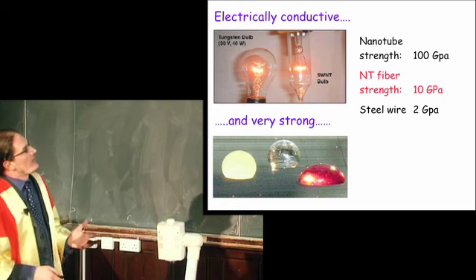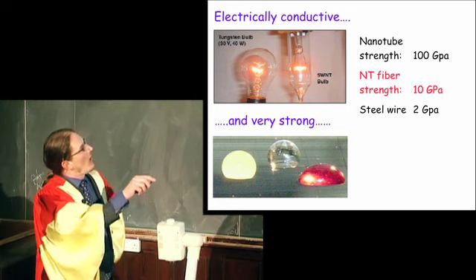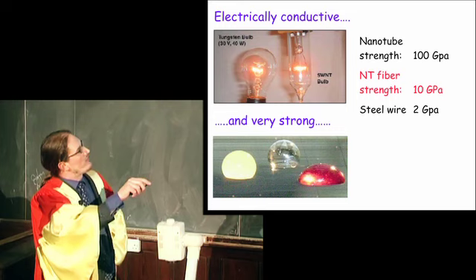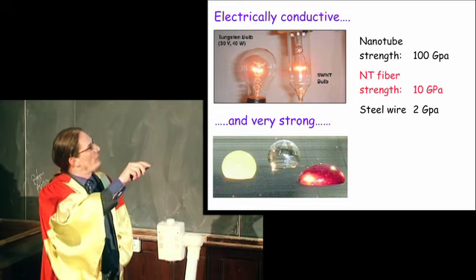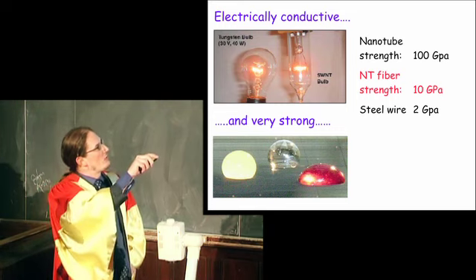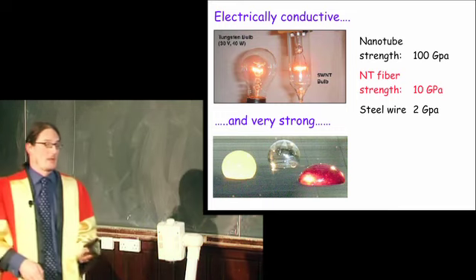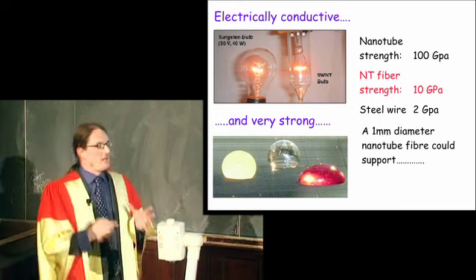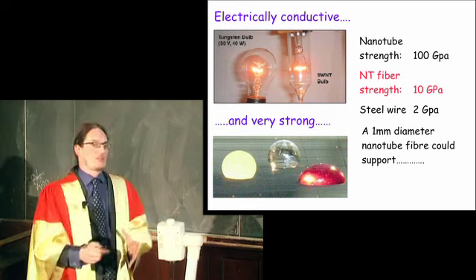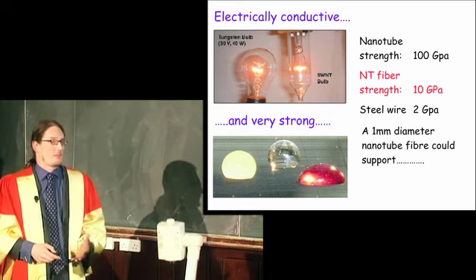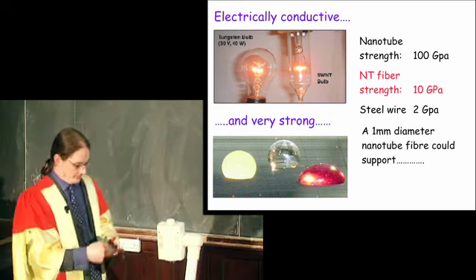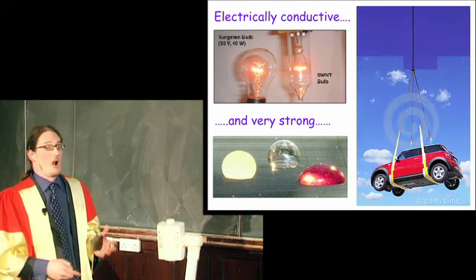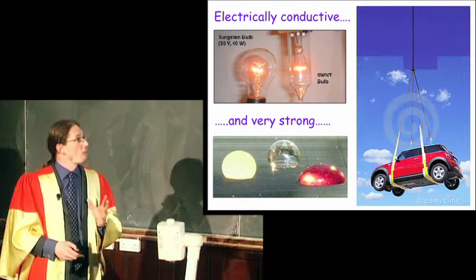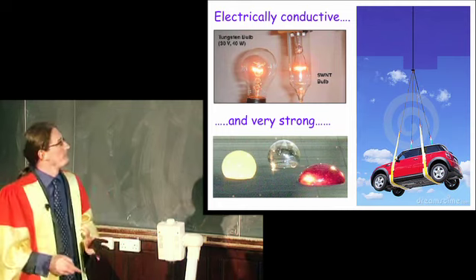Now, these things are really strong. So nanotubes are about 50 times stronger than steel, and people have shown that these fibers are not quite as strong as individual nanotubes, but about 1/10 of the strength. And to put that in context, if we could make a 1 millimeter diameter fiber from these nanotube fibers, that could support a small car. So these things are really, really strong.